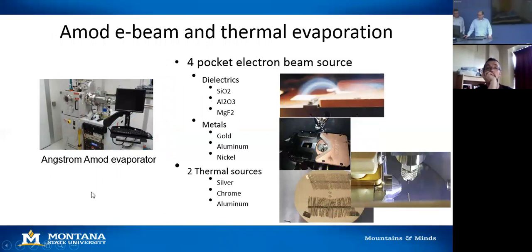A little more sophisticated tool, significantly more in fact, is called an AMOD, electron beam thermal evaporation system. The tool's computer controlled. It has rate control. And instead of just having a way of thermally heating a material with a tungsten filament, it actually has a source of electron current. So in this case, from the picture from left to right, you have electrons coming out from underneath from a filament. Magnetic field turns that current into a target of material. So down here you see a nickel material that's been melted that you would use then as your evaporation source.